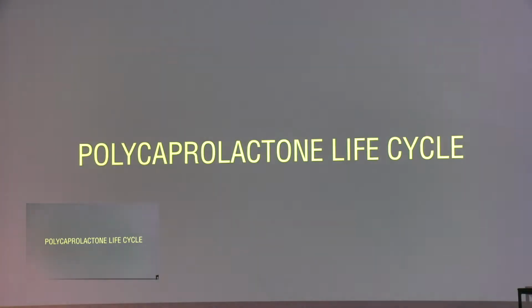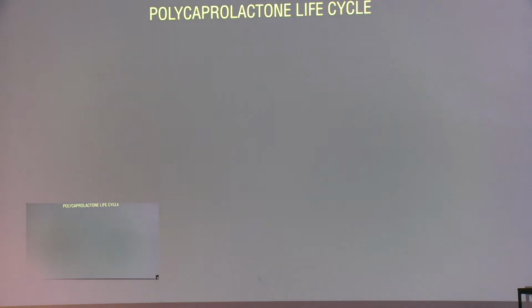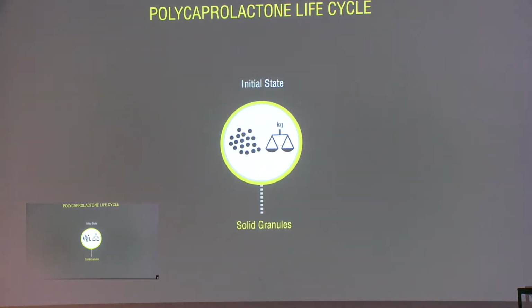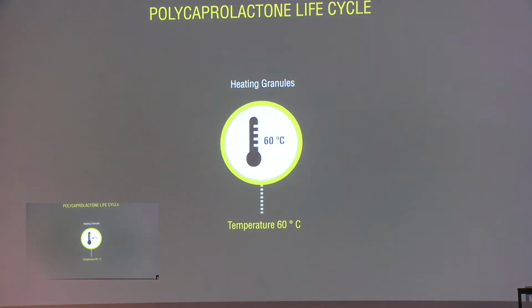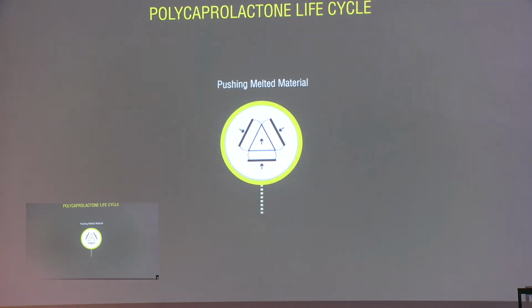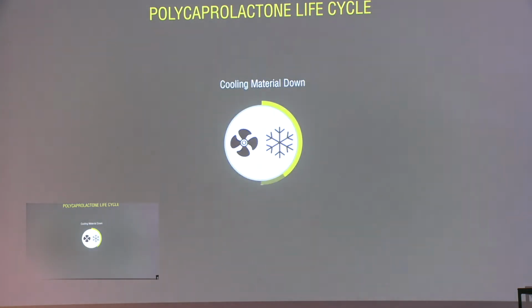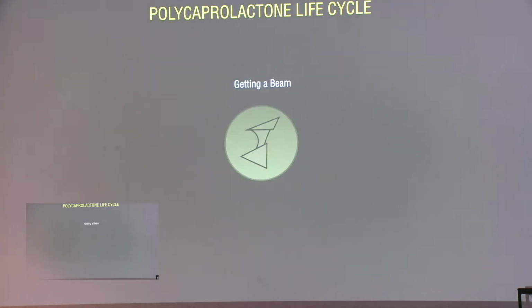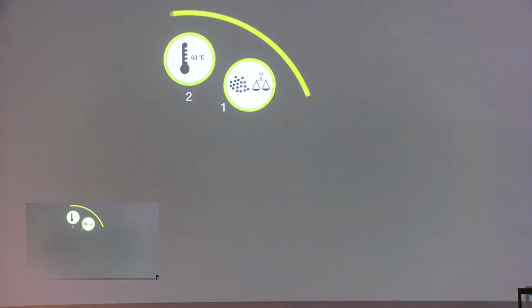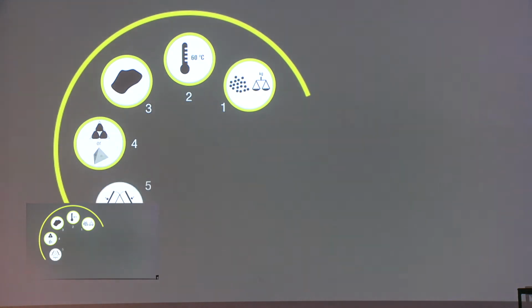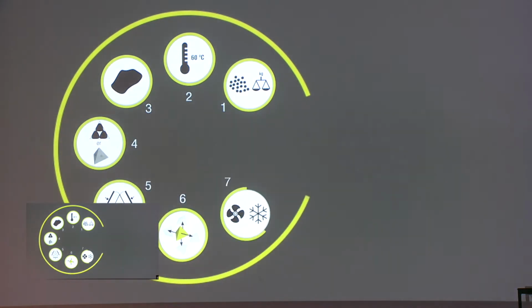So summarizing, how is our technique? We are taking the solid granules, heating them at 60 degrees, melting them until getting the viscous mass, depositing the material on rigid plates or tetrahedrons, pushing the melted material inwards to the nodes, pulling the melted material to reach a position, cooling the material down to reach the beam, and the loop can be repeated to create the lattice. So it gives us a cycle which leads to reusability.